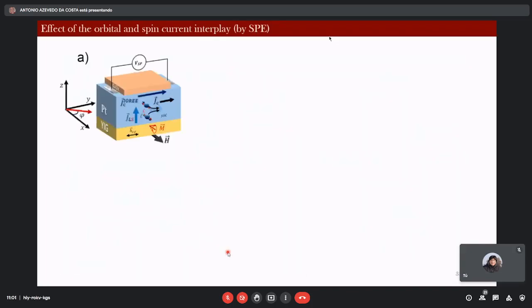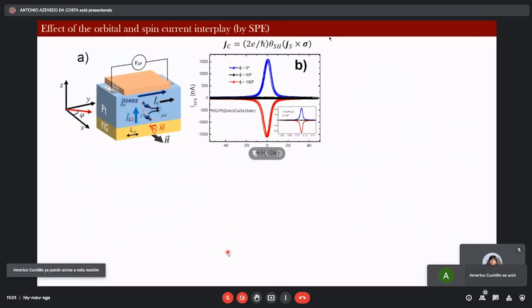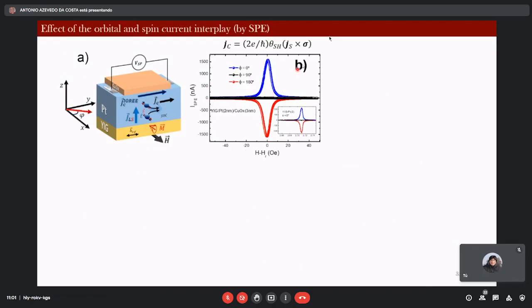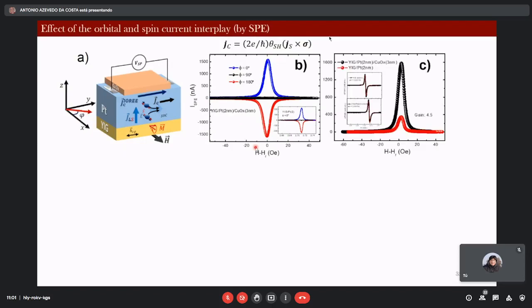We also performed the same measurement using ferromagnetic resonance driven spin pumping. And as I showed before, this is the signal obtained. One important message here is that a pure spin pumping signal has to obey this equation: maximum at 0 degrees, 0 at 90 degrees, and maximum negative, inverting the signal, at 180 degrees. And this is the result I showed before.